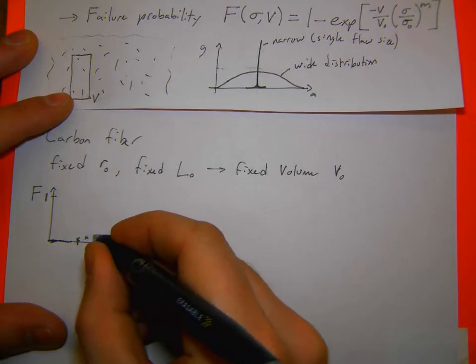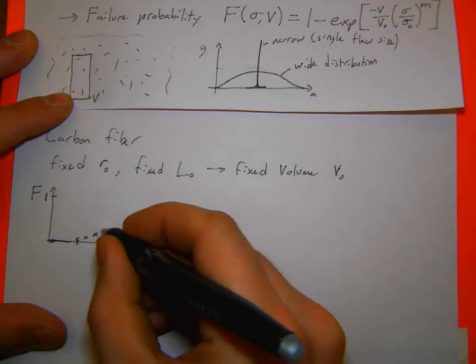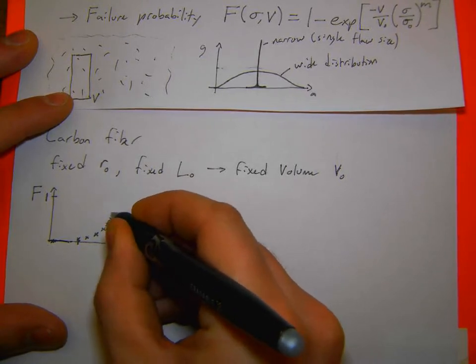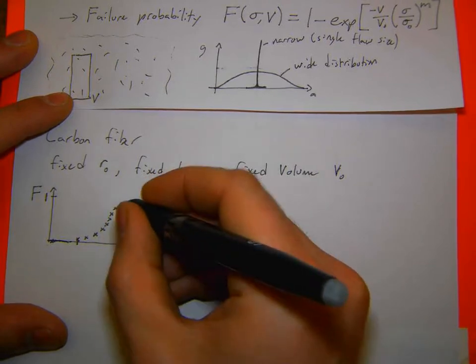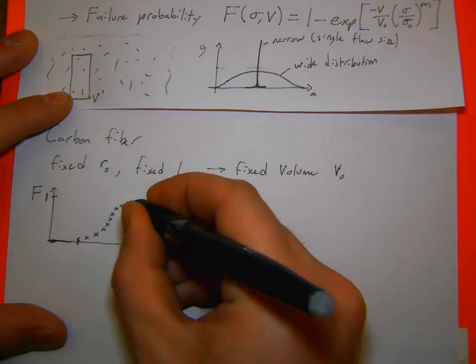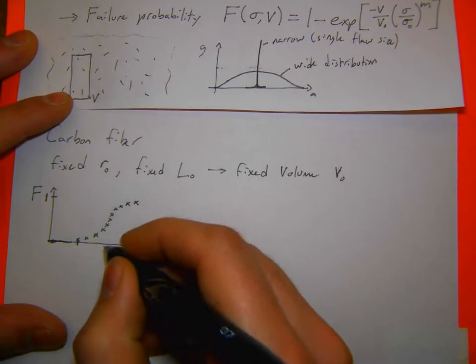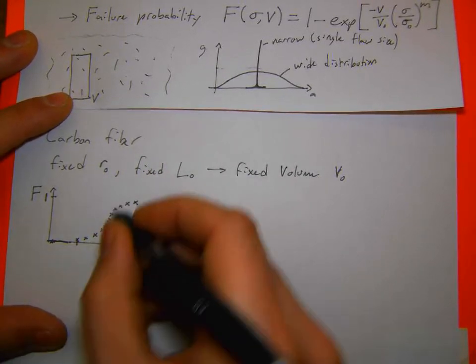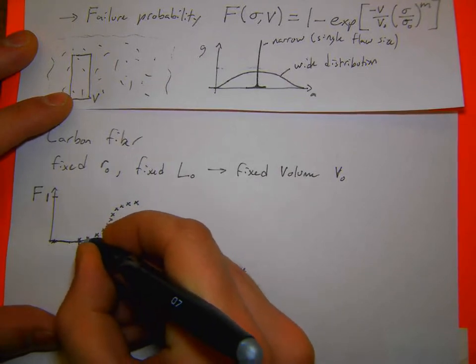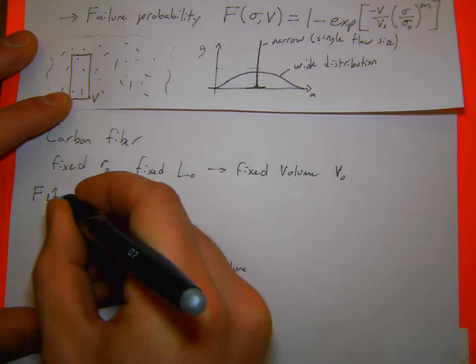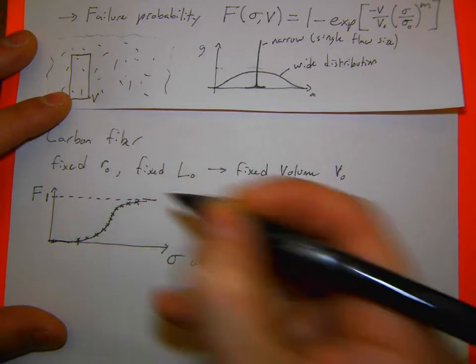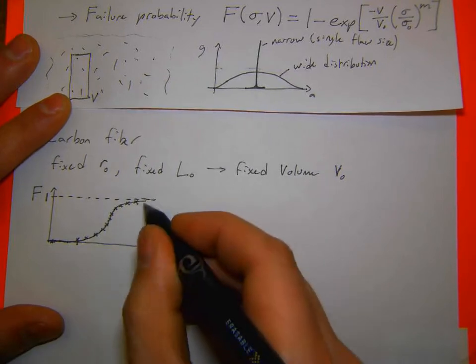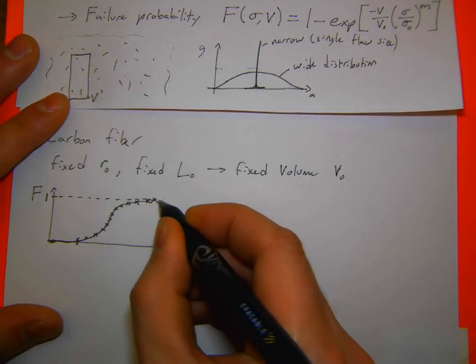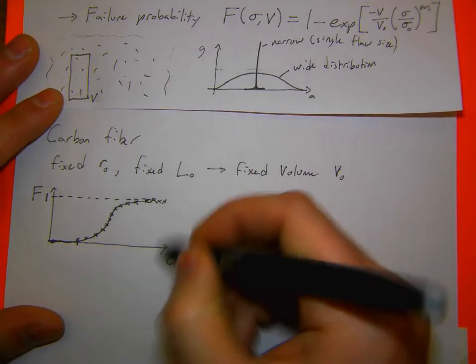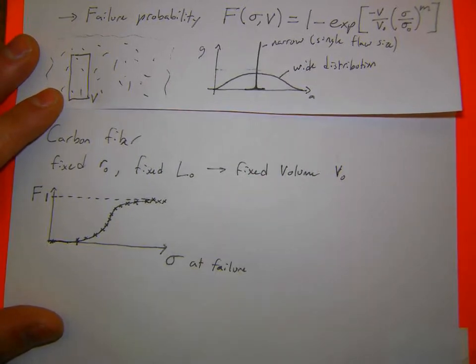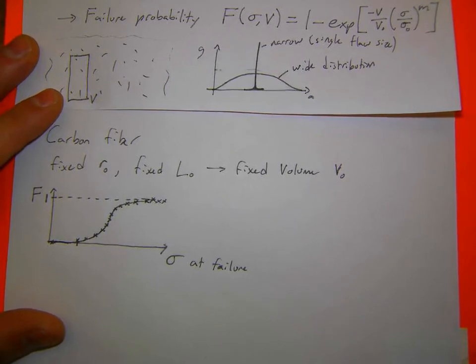So you have some fibers failing at low stresses. Eventually you get to some stress where a lot of them start to fail, and then some of them may keep surviving well after that kind of stress where most of them will fail. And so you get this sort of S-shaped distribution, which now I'm going to draw a line through. Eventually it tails off. So if I get to some very high applied stress, all of them will have failed. By the time I'm applying like 5 gigapascals or 10 gigapascals of stress, all of them will have failed.